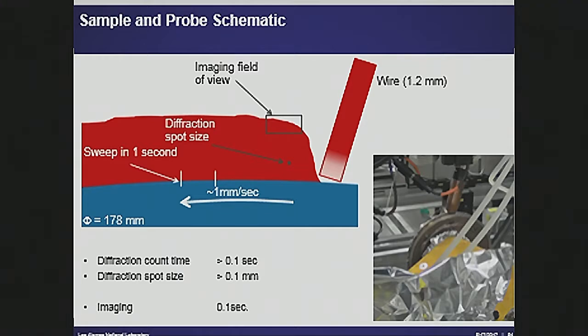It's not fast enough to actually get everything as it goes by, right? So we had the wheel going, we started the welder, and then we made measurements with a diffraction spot and then with an imaging field of view, and although it doesn't show it in the movie, I take this imaging field of view and I drag it down here, we move it backwards and forwards right now. This right now is proof of principle that you can do it. The diffraction data, which I'll show you second, you can actually get more data out of it.